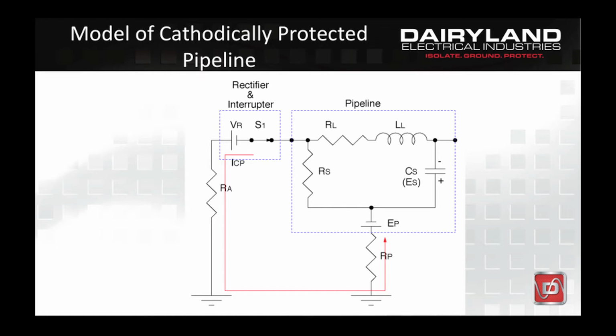Cathodic protection is provided by the rectifier labeled V sub R and an anode bed with a resistance to earth R sub A to remote earth. The switch S1 represents a switch that can interrupt the current from the rectifier with a pre-selected on and off time. On the right side of the schematic, inside of the dashed blue box, are the basic pipeline parameters. R sub L and L sub L represent the pipeline longitudinal resistance and longitudinal inductance.